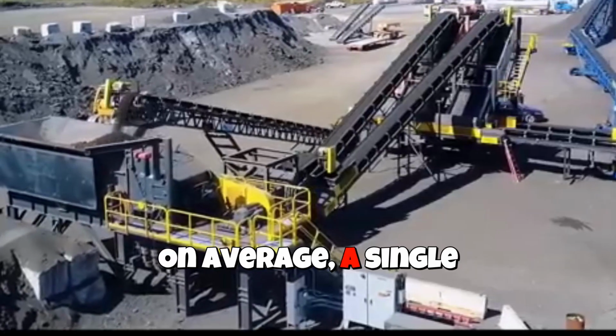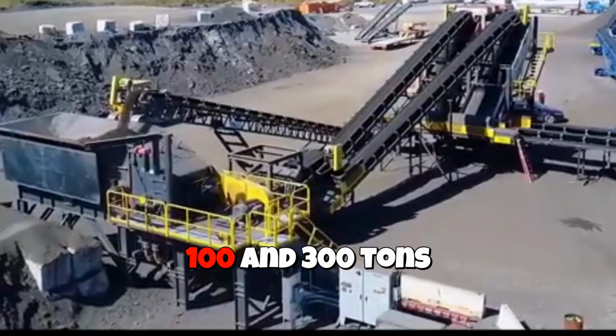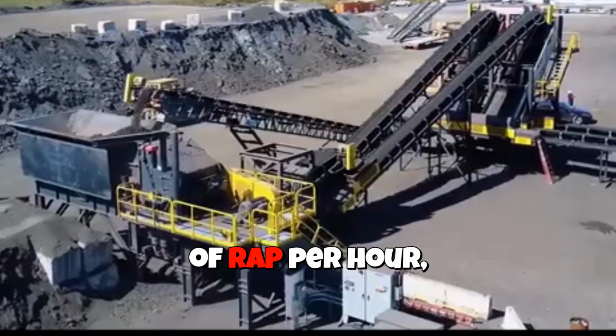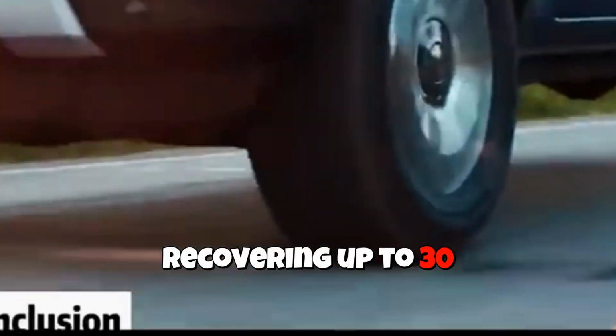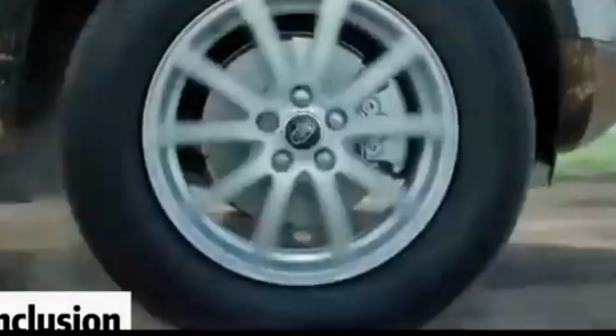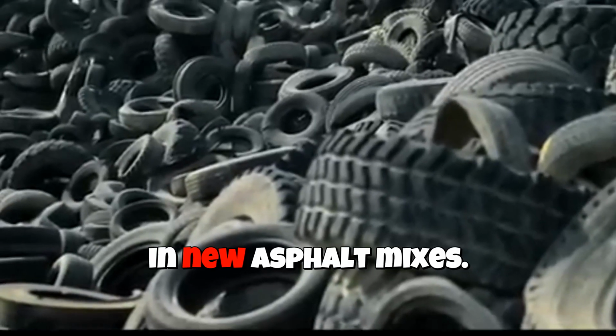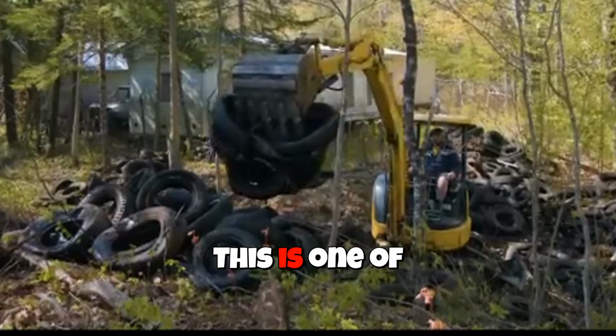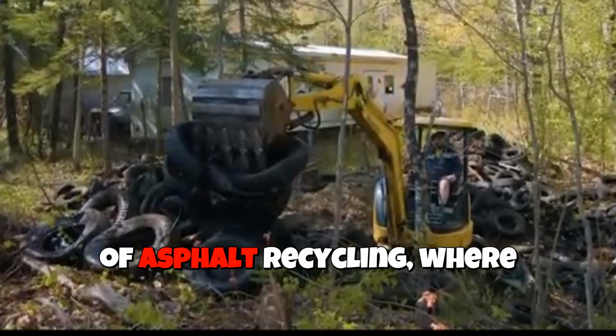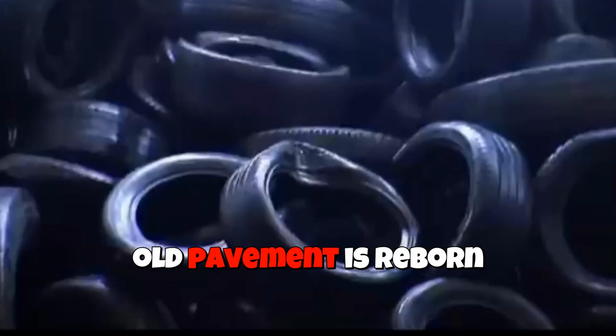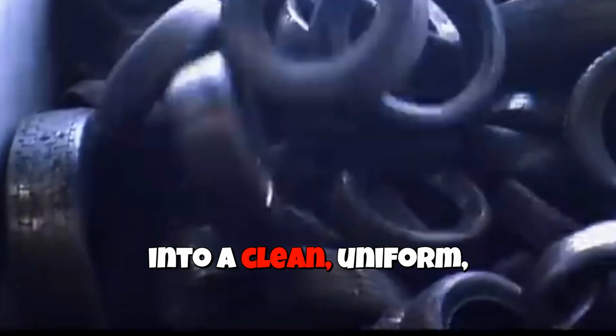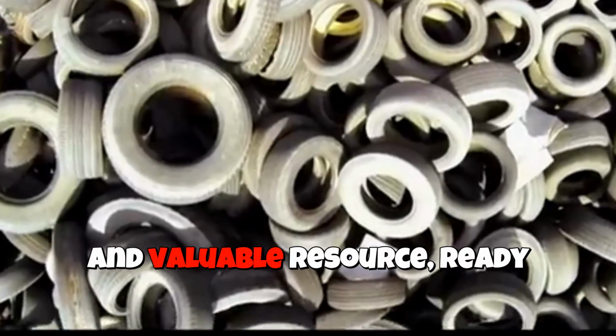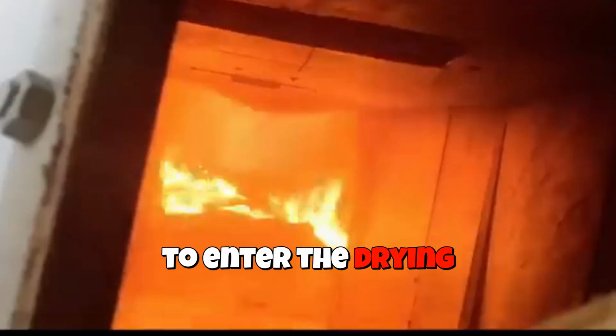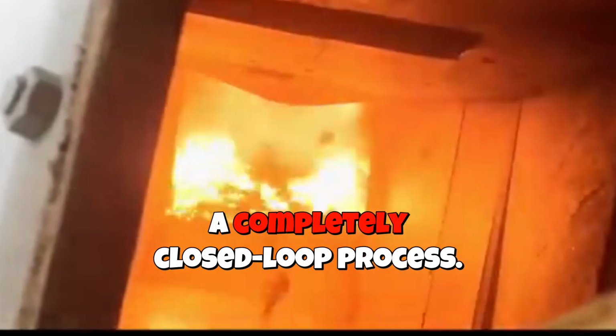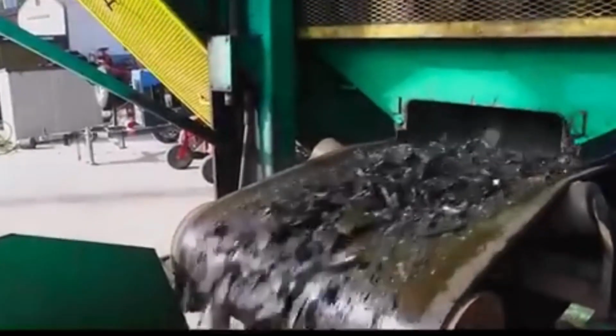On average, a single plant can process between 100 and 300 tons of RAP per hour, recovering up to 30 to 40% of material ready for direct reuse in new asphalt mixes. This is one of the most critical stages of asphalt recycling, where old pavement is reborn into a clean, uniform, and valuable resource, ready to enter the drying and heating phase of a completely closed-loop process.